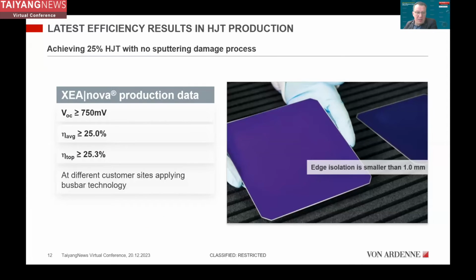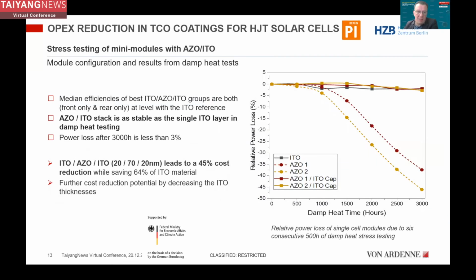So when it comes to heterojunction, you saw all the nice efficiency reports out there. Here we have very standardized production data with busbar design, where our customers achieve VOCs of 750 millivolt and average efficiency of more than 25% and top efficiency of more than 25.3%. For sure, if you get rid of the busbars and use other technologies, you achieve higher efficiencies there as well. However, OPEX reduction is a critical point here, and this was also mentioned in the presentations before. To get rid of indium or reduce the impact of indium in the overall cost of ownership is a big topic.